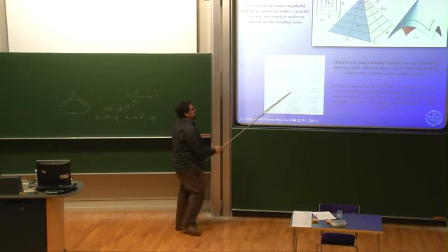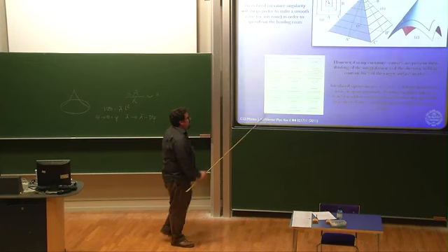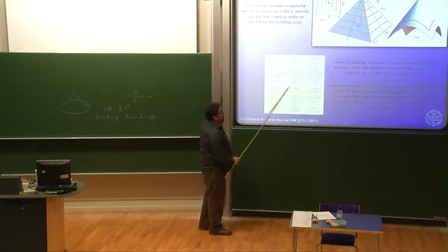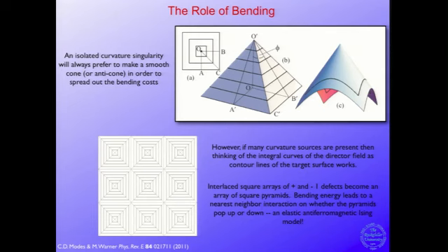because we're in the thin sheet limit, even if you do have a small thickness, that stretch wins out over the desire to spread out that bend, and you do get folds here. So you actually get an array of pyramids. Now you can pop the pyramids up or down, and if they pop in the same direction, you get a fold between them. But if one's up and one's down, there's no fold. And so the bending energy gives you an antiferromagnetic Ising model on this kind of elastic system, which is cute, but I'm not entirely sure how much is useful. But it gives you an egg crate.